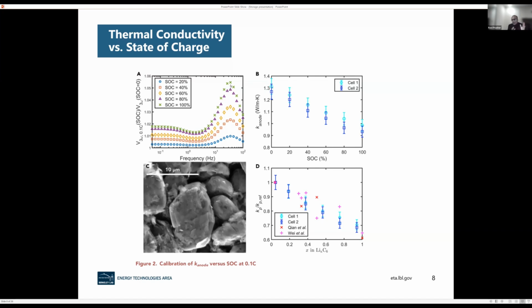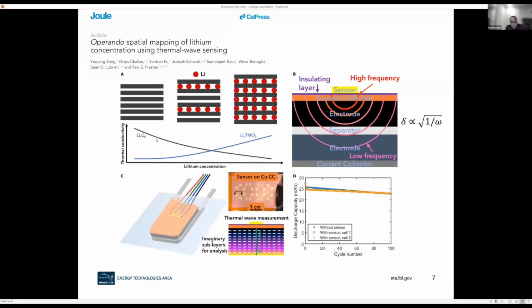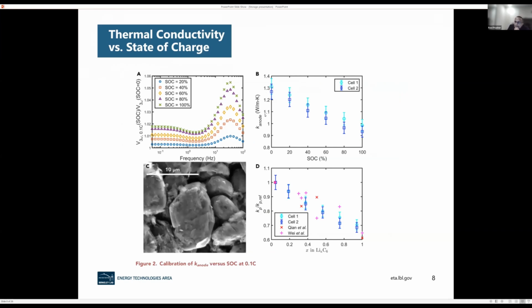So from here, by fitting a thermal model, we can figure out how the thermal conductivity of the anode changes with the state of charge, okay? Which basically means that as more and more lithium goes in, the thermal conductivity is decreasing. It goes back to the behavior that I mentioned earlier, if you can see it, right? So now I have K anode as a function of state of charge. And then we also compared that with some molecular dynamics studies, and they match very, very well. So this is right here, the comparison with molecular dynamics studies, right? So this curve here is our calibration curve. I know how K anode, the thermal conductivity of the anode, changes with the state of charge.